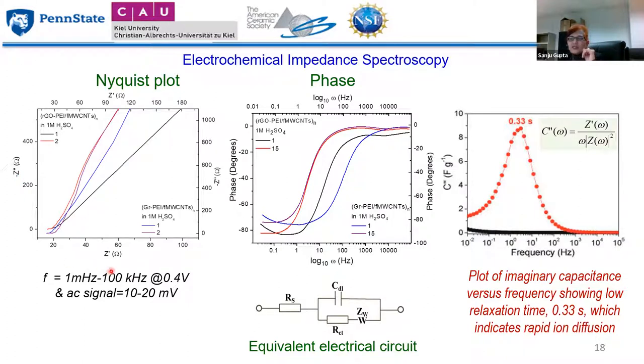In the impedance spectroscopy, we plot the imaginary part of the impedance versus the real part of the impedance. This is the Nyquist plot, and this is the phase plot. By modeling this with the equivalent electrical circuit, we can determine all these parameters, which provides further insight into the dynamical process occurring at the interface. And of course many other parameters, for instance by plotting the imaginary part of the capacitance with frequency, you can determine the time scale. As you can see here, we obtain 0.33 seconds, which is a really great response the very first time. In fact, it attracted the attention of NASA, and we collaborated with NASA on this material.